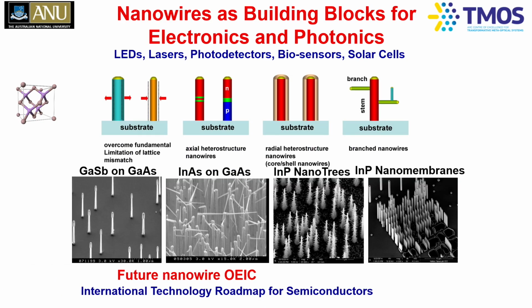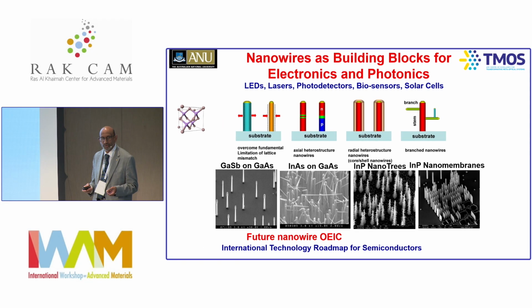So we are going to look at nanowires and nanostructures, and nanowires are seen as the building blocks for the next generation electronics and photonics. One of the unique things of nanowires is that lattice mismatches are no longer an issue, particularly because of their nanoscale interfaces. A lattice constant is a unit cell of the crystal, which repeats itself in all 3 dimensions. And normally when you make 2-dimensional materials, you always have to worry about the lattice constant differences. You can introduce some amount of strain, and beyond a certain amount, they lead to dislocations. That means those materials are useless as far as optoelectronic devices are concerned.